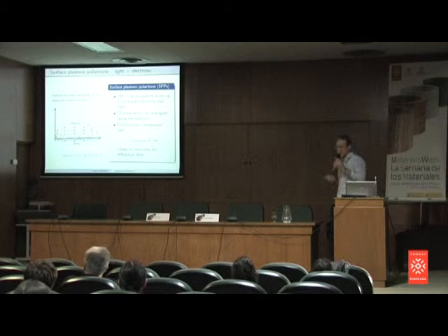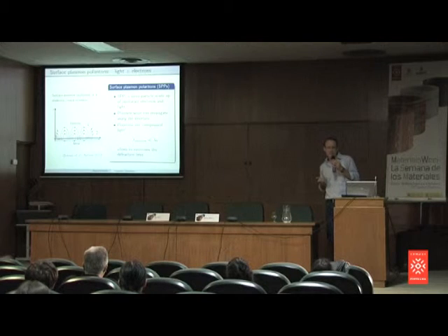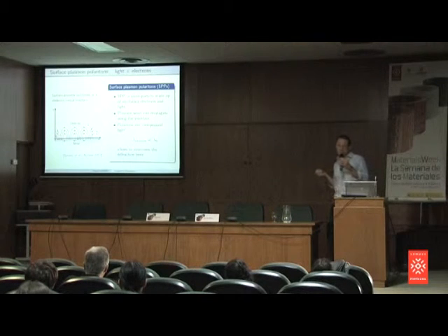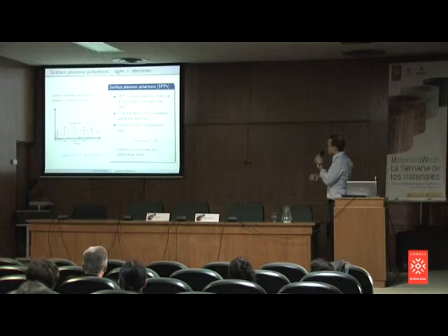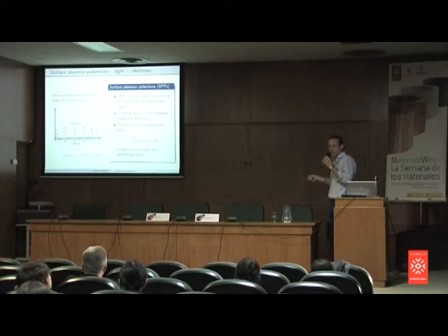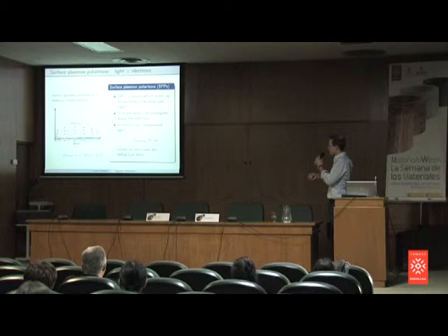Plasmons. What are plasmons? Their full name is surface plasmon polaritons, as written here. I call them plasmons for brevity, and they are essentially light waves, let's say, which are trapped to the surface of some conducting material, because the light interacts with the electrons in there. And that's just what we see here. Now you have a piece of metal, you have electrons inside there, and now if these electrons oscillate collectively, they make a movement like this, no?